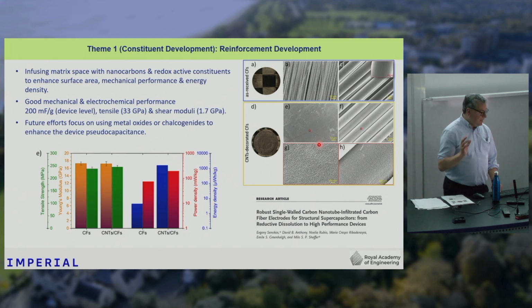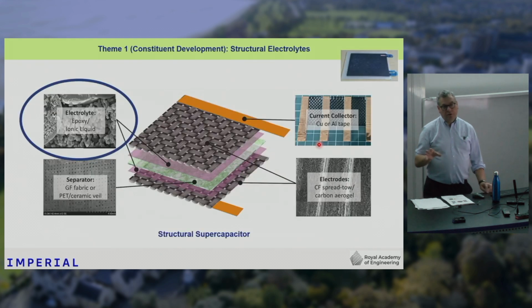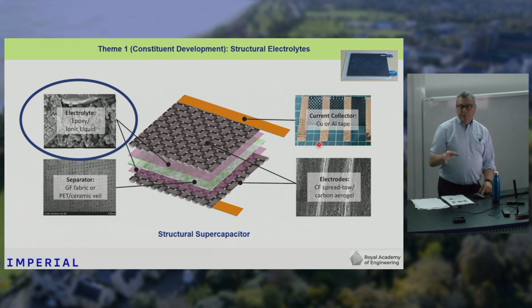But where the really big research challenge is on the electrolyte. So the nice thing about the carbon aerogel is that we've identified the carbon aerogel is actually stiffer than a conventional epoxy. The carbon aerogel has a modulus of about 25 gigapascals. A conventional epoxy has a modulus of about 5 gigapascals. So we actually think the aerogel could be used to enhance mechanical properties of the composite if we can get rid of this degradation problem. And so that synergy there between mechanical and electrochemical is really attractive. It offers us a way of actually getting this technology to go beyond just a rule of mixtures.